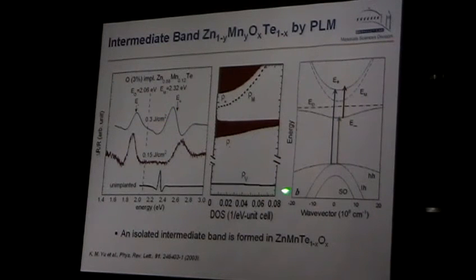So we see now transitions, and we identify this transition as a transition from the valence band to the intermediate band, and this is the low energy transition, and from the intermediate band to the upper band. And this is the high energy transition. We still don't have this transition because we don't have electrons here. We need to occupy this state. But that was a really very successful attempt. We are very happy with this because it indicated that such materials can be produced. And you see, in this case now we have a pretty narrow band, well separated from the conduction band.